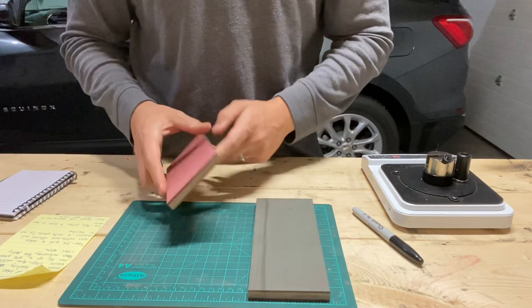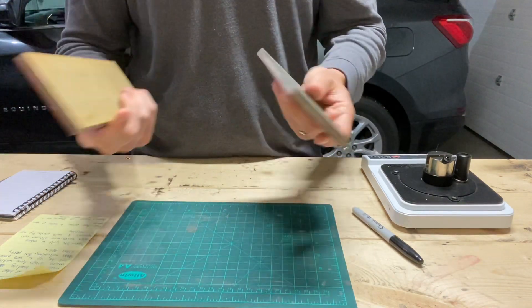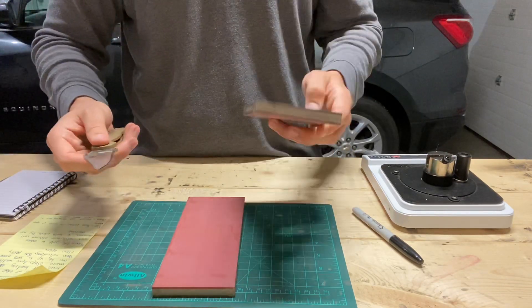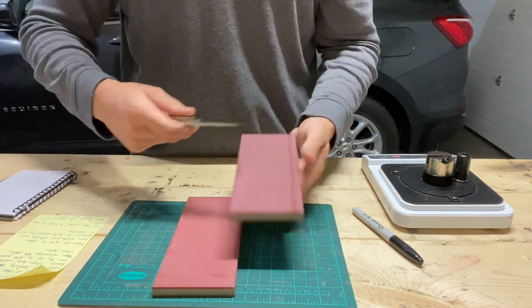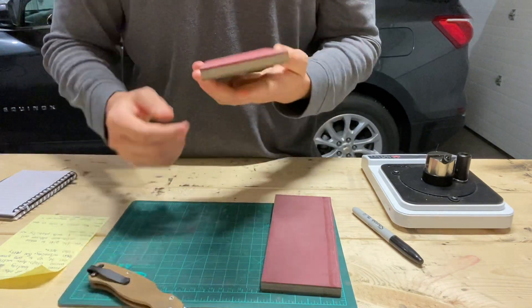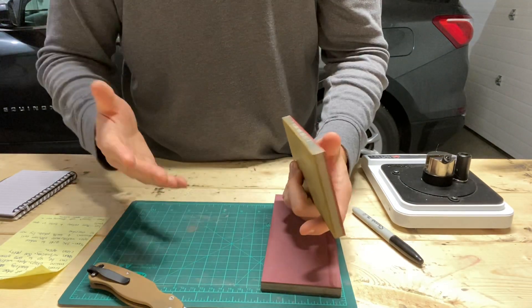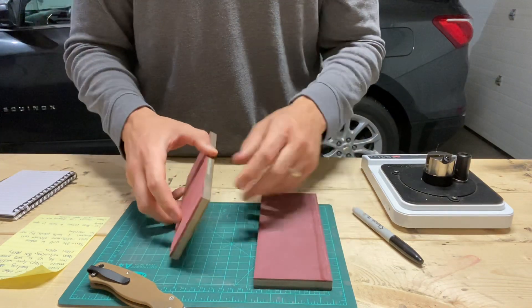Let's go through a progression. I'm just going to use these for demonstration purposes. You go through your normal progression with a knife — got the 10V PM2 here. So your coarse grit, 240F, then up to 400F, 800F, 1200F. You finish on the 1200F stone, which is a 2 to 3 micron stone — that's about a 3 to 4K finish in terms of JIS, Japanese industrial standard.